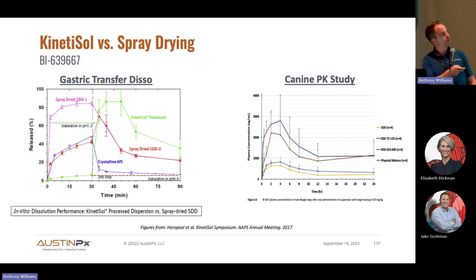And what we notice here when comparing the KinetiSol process material, this green line, versus the spray dry dispersion. Both versions of the spray dry dispersion show, even though it's an enteric polymer, it's all HPMCAS based, right? It should be protected from acid release. There's significant release of the drug in the acid phase, whereas with KinetiSol, you see almost no release in acid.